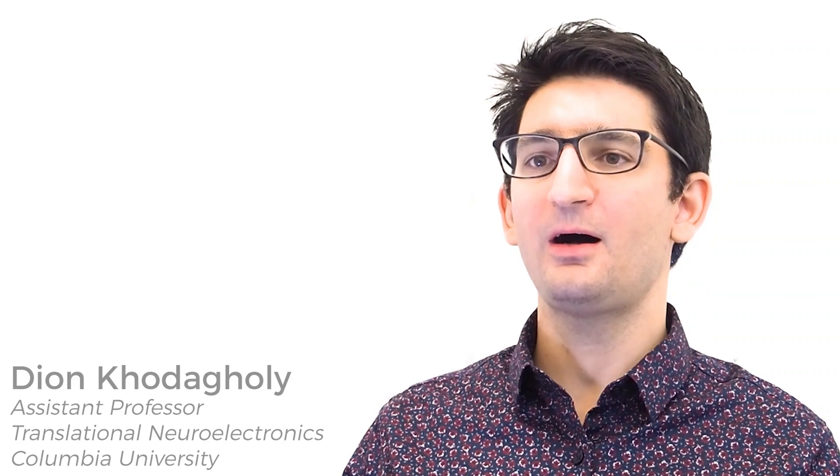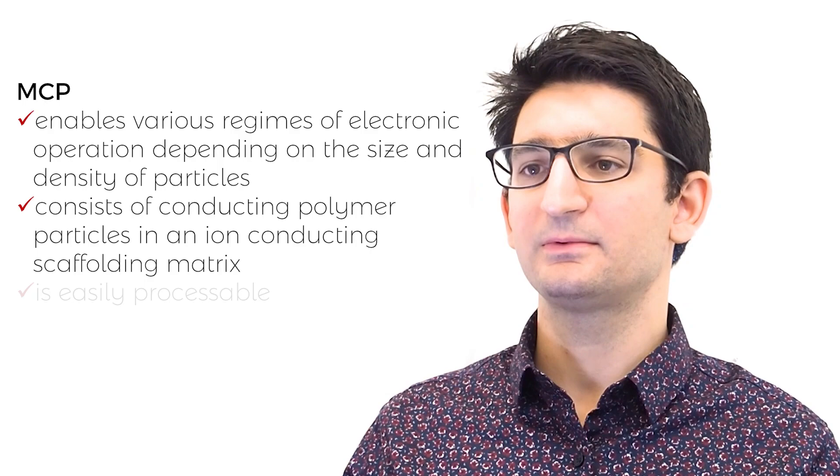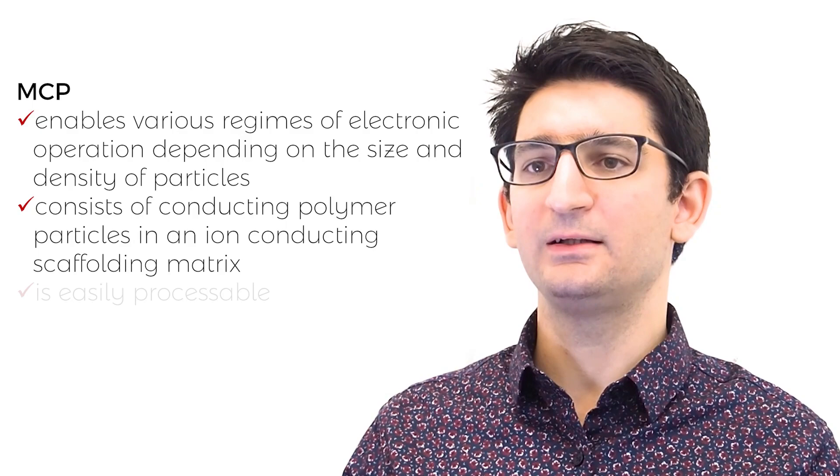In this study, we developed a novel soft biocompatible composite material, MCP, that can serve as different electronic components depending on the size and density of constituent particles. The key components of MCP are conducting polymer particles and the ionic conducting scaffolding matrix, enabling high conductivity and ionic interactions through doping and de-doping.